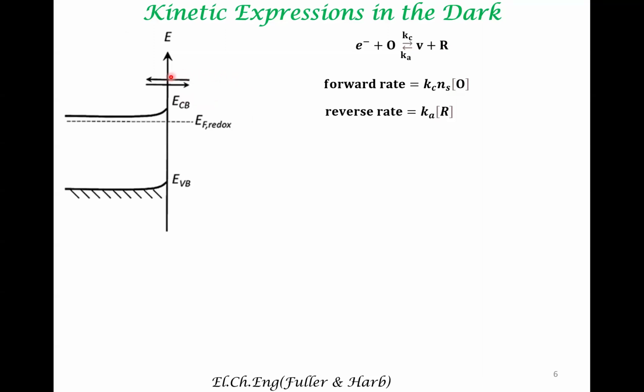That is, a large number of vacant energy levels are present in the entire conduction band. So by change in occupancy of the conduction band, the number of levels is not significantly changed. Therefore, this can be more or less taken as a constant and incorporated into this rate constant Ka. Therefore, we neglect the variation of V because it is more or less a constant independent of voltage. And so the reverse rate is represented by a constant times the concentration of R, right? So what is important to notice is that this quantity is critically dependent on potential, but the reverse rate is more or less independent of potential.